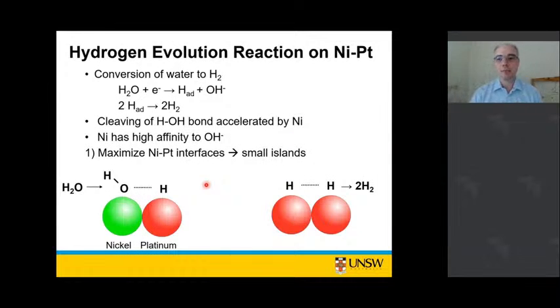And our motivation for this was the opposite reaction, the other reaction to the OER reaction. This is the hydrogen evolution reaction. And nickel platinum structures are really, really good catalysts for hydrogen evolution. So this is the reaction where you're taking water and essentially breaking that hydrogen oxygen bond, and then forming your hydrogen gas at the end of that. So nickel platinum together is a very effective catalyst, because when you have your nickel next to your platinum,